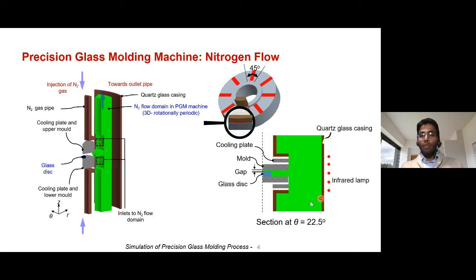Now, if you look at the figure on the right hand side, you can clearly see the slots through which the nitrogen gas comes out. I'm showing a 2D sector, at an angle of 22.5 degrees. There are 8 channels, repeating in a rotationally periodic manner. So I'm showing the 45 degree solid domain over here, and this is the section shown at 22.5 degrees. At 22.5 degrees, you can see clearly the channels through which the gas comes out.